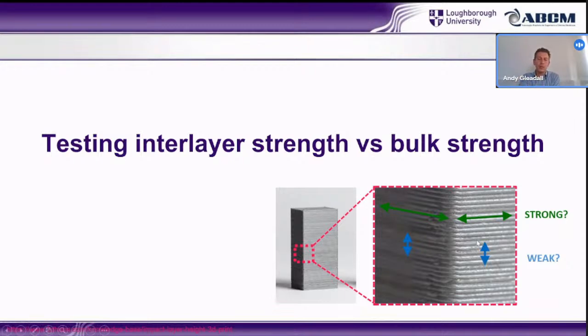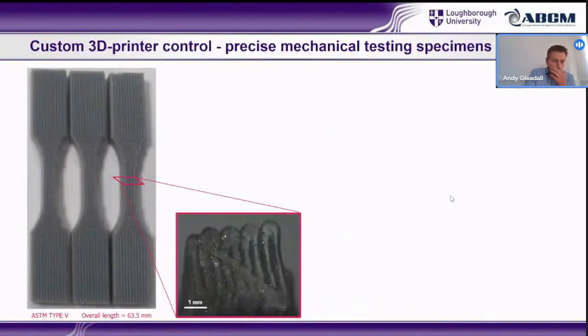The material is weaker when you test it in the Z direction, normal to the plane of the layers, compared to its strength when you test it in the plane of the actual extruded filaments. So I had a student project look at this when I was first here at Loughborough, and printed the ASTM specimens using standard slicing software. And when you fracture them, you get a really nice, clear view of the actual bonded area.